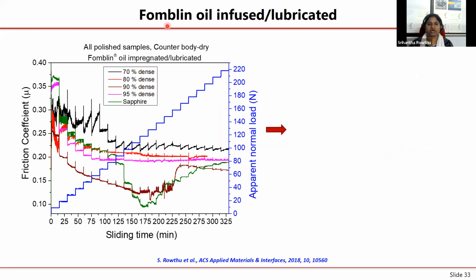That means I'm going to have 70%, 80%, 90%, 95%, in fact, 99.5% dense samples. Seems like I didn't put the latest graph. Anyways, and then you also have a sapphire single crystal sample. Of the first three cases, obviously it is an infused case, and the last two cases are actually a coated situation or a lubricated situation. So this is all the friction coefficient data.